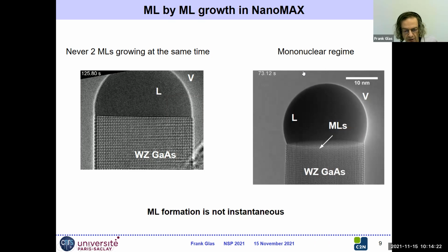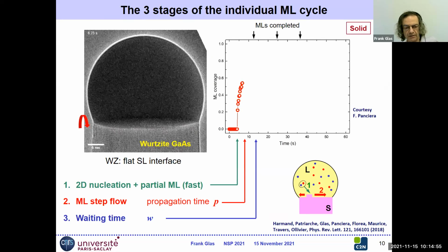However, it's quite clear from videos such as these, you can see the monolayers propagating across the interface. So our old picture that the formation of a monolayer can be considered as instantaneous is clearly not valid, at least in these small nanowires. There might be instances where it's valid, but in the case that we are observing here, it's not valid because the propagation of a monolayer across the interface takes some time. So the picture we had before has to be revised. So let us be more precise.